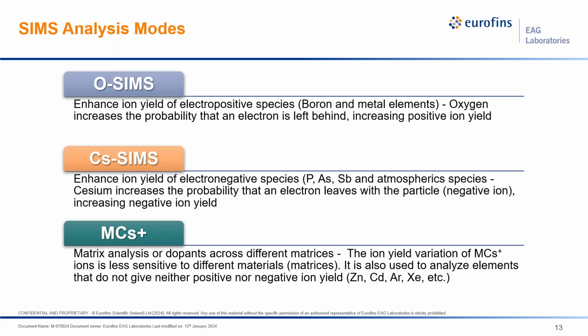That means we are measuring a cluster of the implanted cesium ion with whatever element we choose, in positive ion detection. This mode allows us to measure some things with less ion yield variation, so a little bit closer to the actual composition of the material. It can also be used to analyze elements that don't ionize well as positive or negative ions. Some examples of these are zinc, cadmium, and the noble gases like argon and xenon.